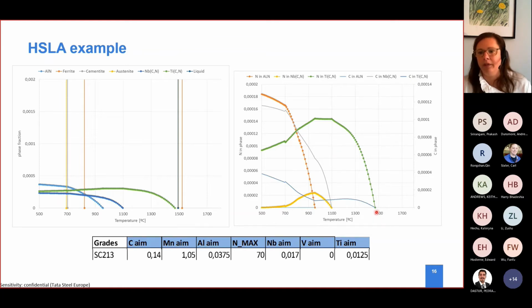Obvious. However, if we follow, for example, the titanium one, at the beginning, this little guy likes to form mostly as a nitride. However, a part of it will be a carbide. But when the niobium one appears, this one, on the opposite, likes to form a carbide and not a nitride, so it will fight together with the titanium for the carbon, but not much. However, when the big boy comes, aluminium nitride, it says, no, I want all the nitrogen for myself. Therefore, it's taking the nitrogen out of the titanium and taking it for itself.